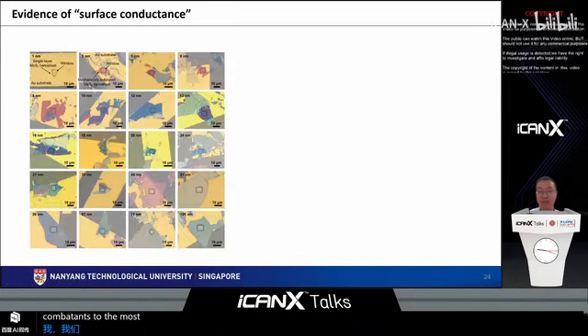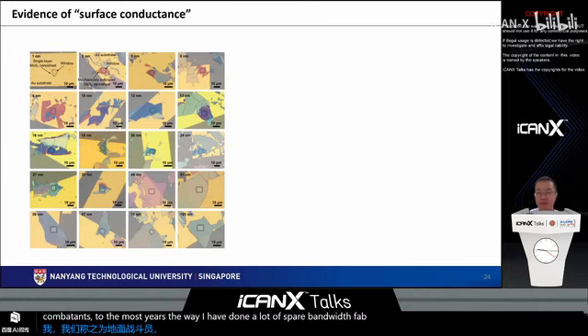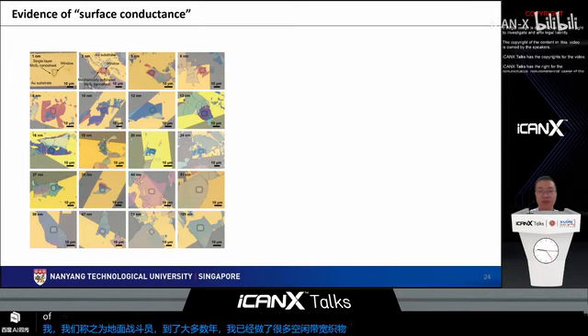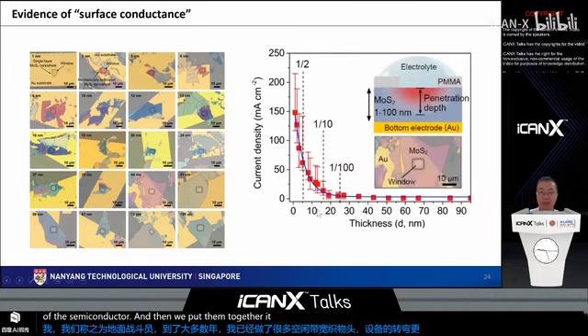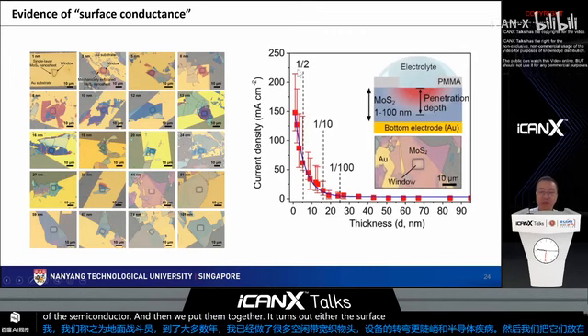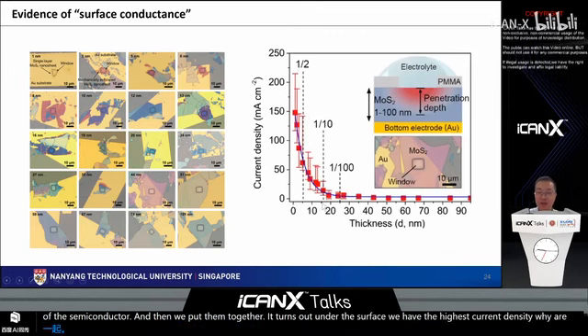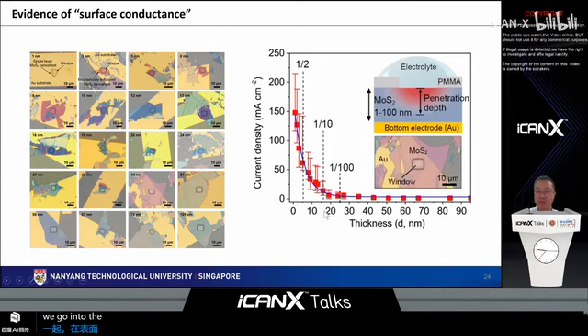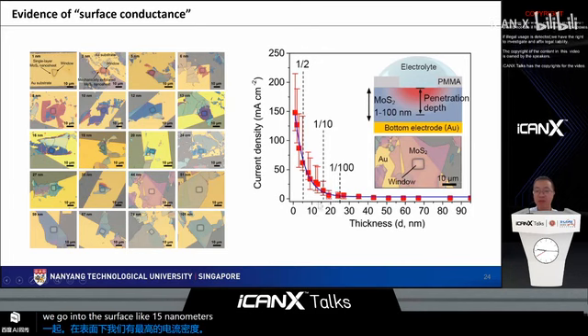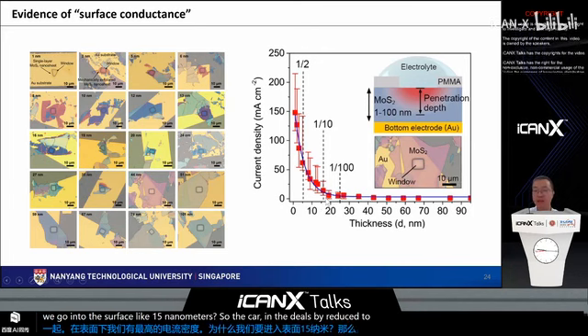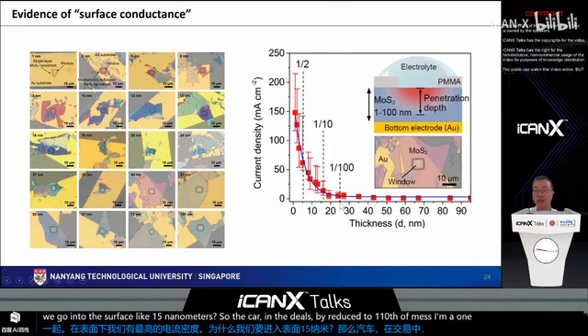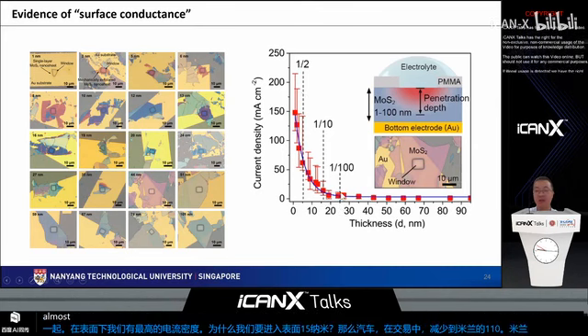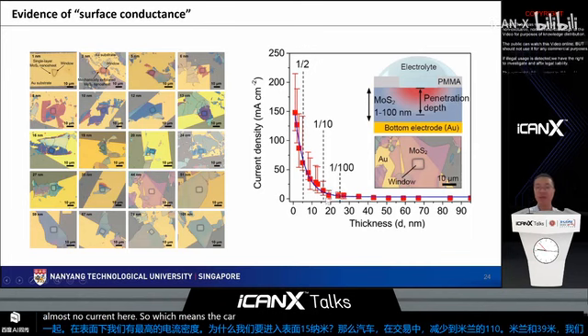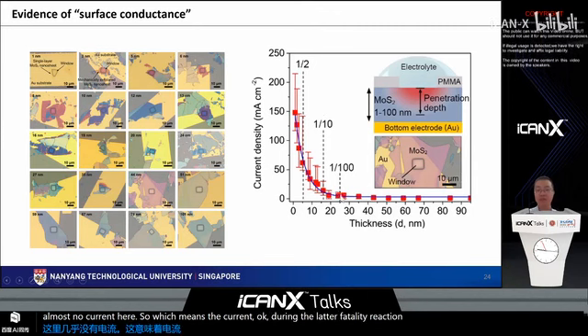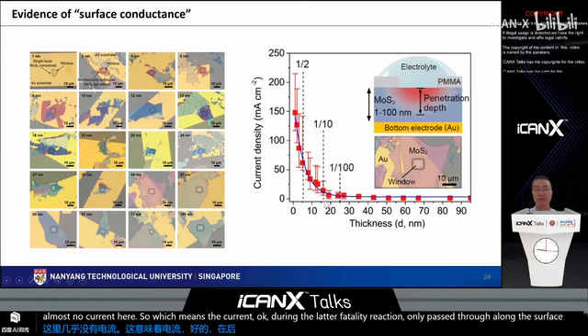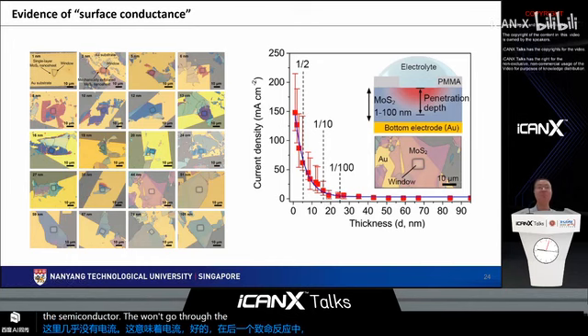To demonstrate, we have done a lot of experiments. We fabricated tens of devices with different thicknesses of the semiconductor, and we put them together. It turns out at the surface, we have the highest current density. While if we go into the material, like 15 nanometers, the current will reduce to 1/10 of the maximum one. And at 25 to 30 nanometers, we get almost no current there. Which means the current during the electrocatalysis reaction only passes along the surface of the semiconductor. It won't go through the bulk of the material.